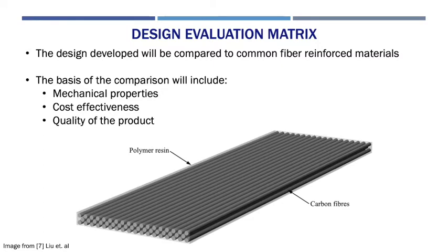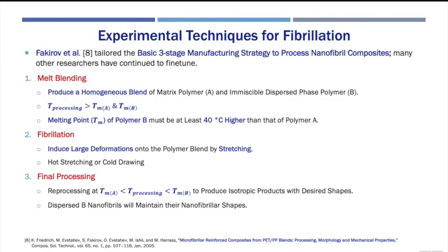The bottom is an example of a common reinforced polymer such as carbon fiber. Fiber-reinforced polymer composites can be produced by a process called in-situ fibrillation. This involves melt blending two polymers to produce a uniform dispersion. This blend is then stretched to produce in-situ fibrils of the dispersed polymer within a polymer matrix. This is done industrially using rollers or blown gas to stretch the polymer.